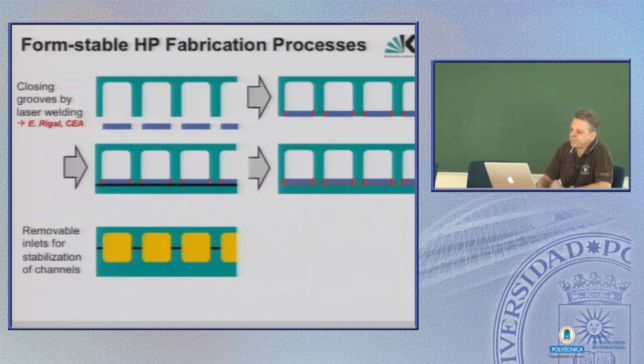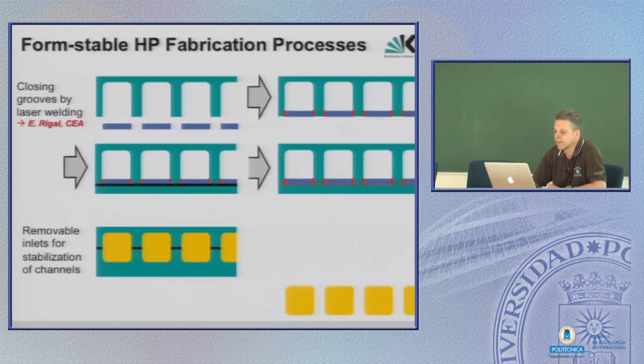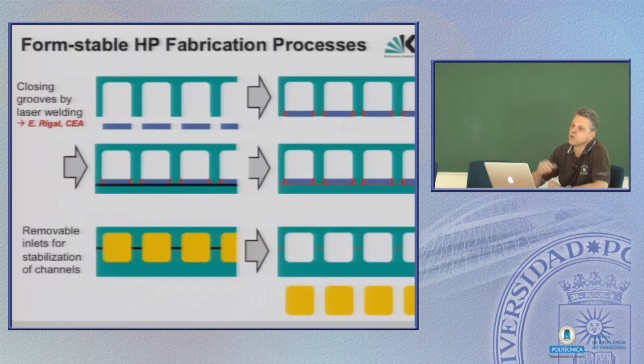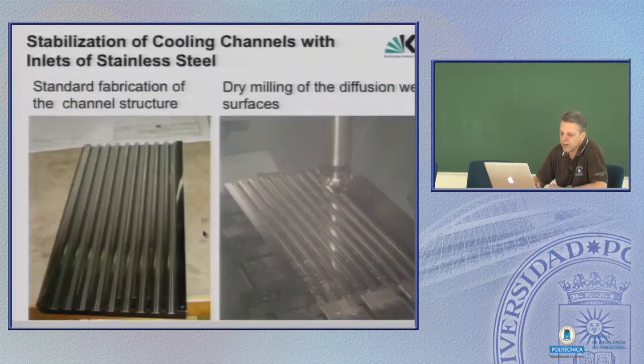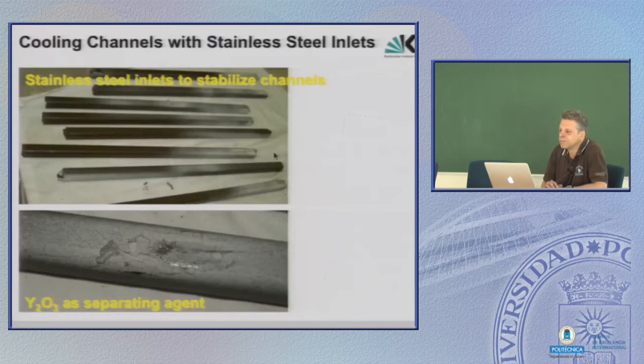Another method from our side was, okay, to prevent the channels from bending, we fill them up. We simply put a massive steel part in these cooling channels, and then you can press the plates together with pressure as high as you want, and it prevents them from deformation, and afterwards you remove the solid parts and you end up with what you want to have. In principle, an easy idea. We have done this, fabricated plates, and we used simply stainless steel, and well, the trick is to remove the parts after welding.